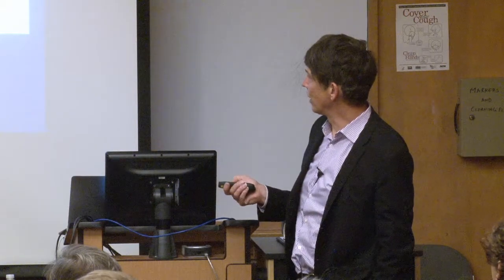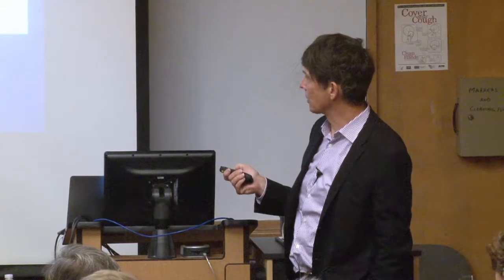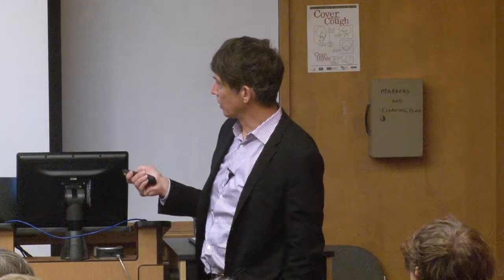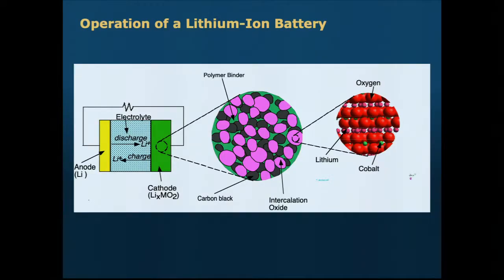So let me give you like a very short primer on lithium-ion. It's essentially a shuttle device for lithium ions. You know, you have an anode where lithium sits at high chemical potential. That's typically lithium in graphite today. And then you have a cathode where lithium sits at very low chemical potential. So if you remember your thermodynamics, the Nernst equation tells you that you can build up a voltage. That's the difference in chemical potentials. And for lithium-ion, that difference is remarkable. It's close to 4.5 volt, which, again, remember, water splitting is about 1.2 volt.